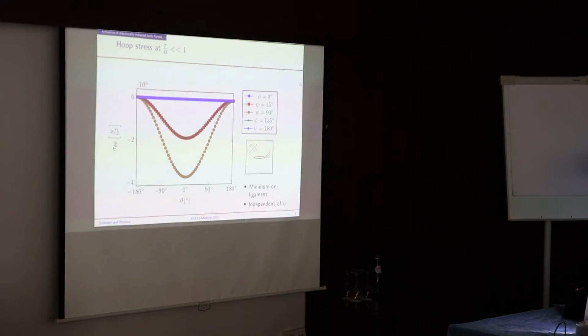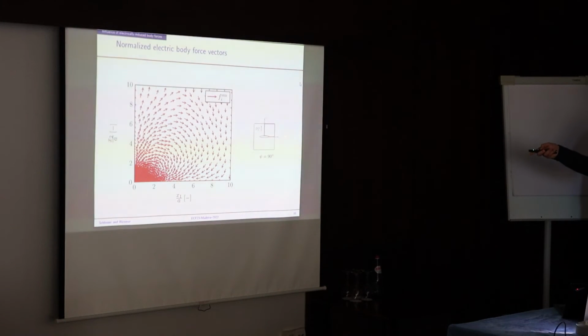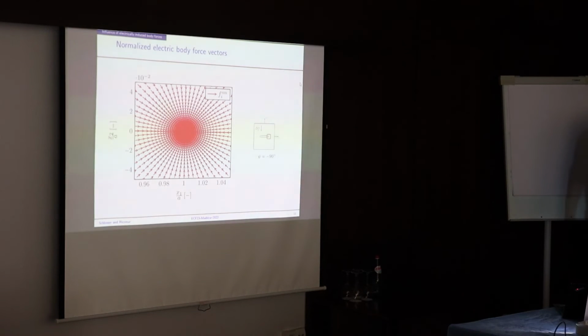to get an idea where these compressive stresses come from. This is the right upper quarter of this plate with the crack. It's rather chaotic. You can't see much, but if you zoom in on this crack tip, you see a radial field of the body force vectors pointing at the crack tip, which is not surprising, because the body force vector had the gradient of the electric field in it, times the electric field, and of course there's a singularity here, and that's what will happen.